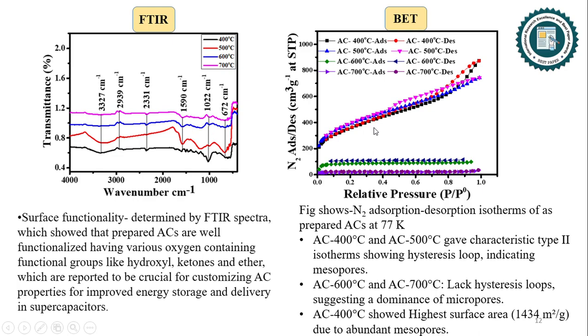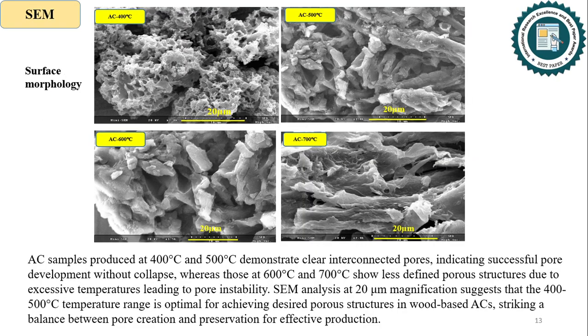So this figure shows nitrogen adsorption-desorption isotherms of the prepared activated carbons at 77 K. As can be seen, AC 400 degrees and AC 500 degrees centigrade gave characteristic type 2 isotherms showing a hysteresis loop, indicating the presence of enormous mesopores, whereas AC 600 degrees centigrade and 700 degrees centigrade lack a hysteresis loop, suggesting a dominance of micropores. So activated carbon at 400 degrees centigrade showed the highest surface area of 1434 meters squared per gram due to abundant mesopores.